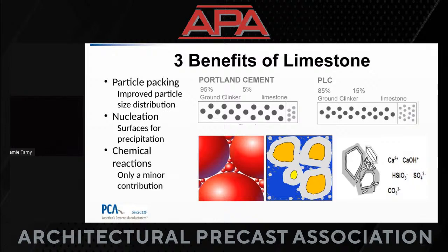So limestone, you can't think of it as a dilution or just this thing that we throw in without thinking about it. There's really benefits of using limestone in cement. As I said, the Portland cement standard allows for up to 5% limestone. So if these are the clinker particles that we're grinding up, we can add a little bit of limestone in. This is just an idealized cement graphic here. We actually add some other materials in as part of the cement formulation too. But if we look at just whatever else is in there versus limestone, 5% limestone, we always have to stay below that limit to be able to meet the standard. So we never quite reach 5%.